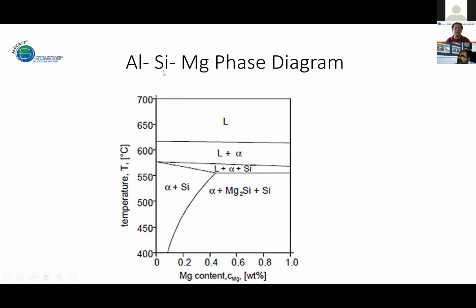Yeah, we are coming to the same again, aluminum, silicon, magnesium phase diagram. When you add magnesium to, let us say, LM9 or LM6, where you are already having about 11.5% silicon. Again, let me repeat, keep the silicon below 12. 11.5% silicon. You add a little bit of magnesium. We always have only alpha, Mg2Si and Si. Above 12, above this one, above 0.4, what happens is that the silicon also precipitates in a different form. We require an alpha part. Here, as I explained to you earlier, this also goes into solid solution.